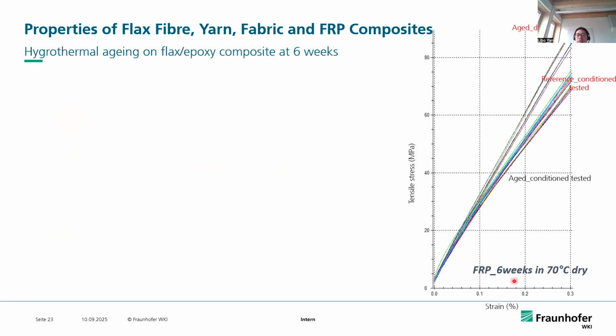In this figure, it shows the flax epoxy composites exposed in the 70-degree oven for 6 weeks. Here are the reference samples without the 70-degree exposure, and those curves are the samples exposed at 70 degrees for 6 weeks. We can see that compared with the reference sample, there is even a slight increase in the strength and the stiffness.